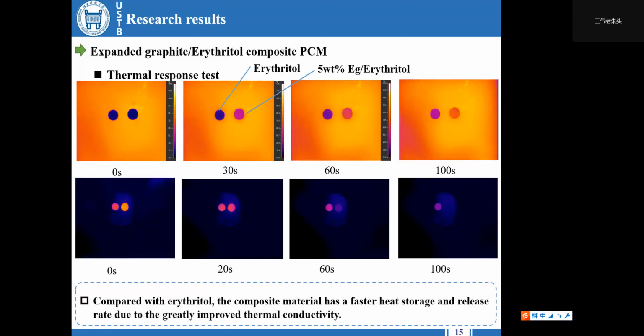The heat storage and release rates of phase-changing materials directly reflect thermal energy utilization in practical thermal energy storage applications. Therefore, constant temperature heating and cooling was used to reflect the effect of adding expanded graphite. Considering that 5% expanded graphite erythritol has the best phase change properties, mechanical properties, and thermal conductive properties, this material was compared with erythritol, and an infrared camera was used to observe the thermal response properties. Through experiments, it can be clearly observed that the composite material has a great heat storage and release rate because the thermal conductivity of the composite material has been greatly improved compared with pure erythritol.